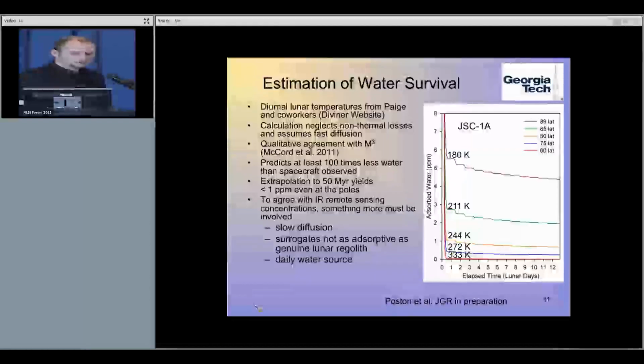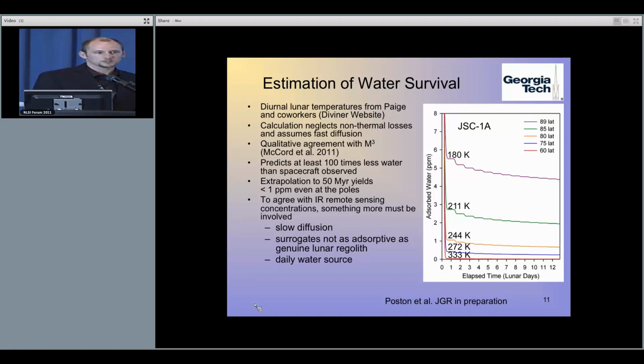In fact, if we extrapolate these data out to 50 million years, we see less than 1 ppm remaining even at 89 degrees latitude. That suggests that a pulse of water early on will not stick around, at least not on the exposed surface. Some things that could help the water stick around are some sort of really slow diffusion process. We don't see evidence for this in our experiments, but that doesn't mean it's not actually happening. We're continuing to look into that.